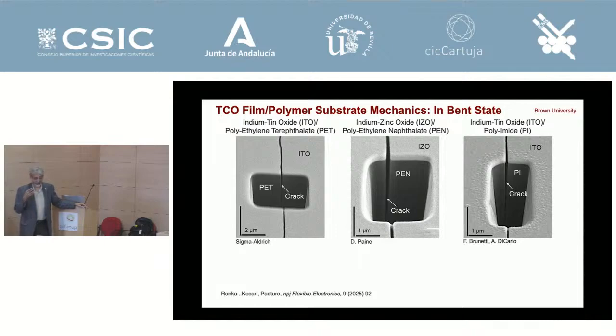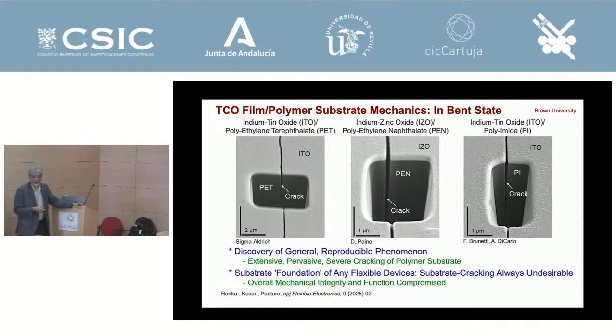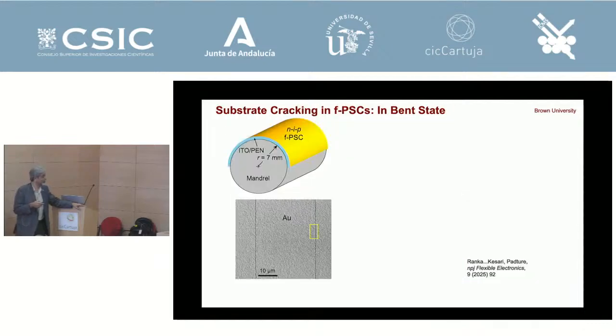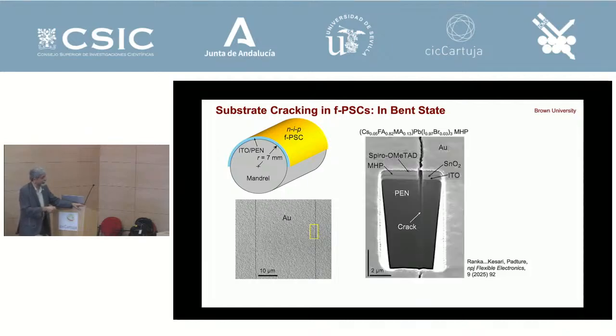And so that's what gave us a clue that this could actually be the problem of degradation of these solar cells: your foundation is degrading, so everything on top of your foundation is also going to degrade, right? Become unstable, right? And so why is this happening? And we thought, Brown University is very well known for mechanics. And so I talked to my colleagues, and nobody could give me a good answer. And then finally I talked to another colleague, and by the way, this is for the entire solar cell. So this solar cell has all the layers. This is the ITO, the tin oxide, the perovskite, the hole transporting layer, and the gold.